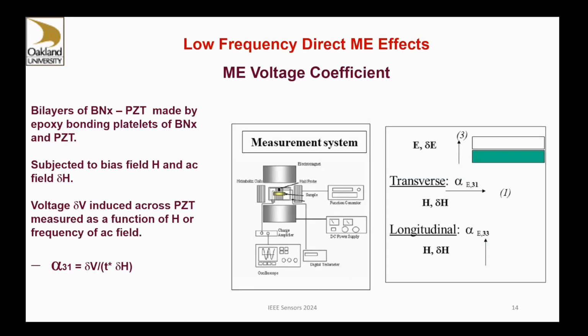So then what we did was to make a bilayer of these ferromagnetic platelets with PZT, and they were bonded by several different techniques, including epoxy bonding and eutectic bonding, and they were subjected to a DC magnetic field and then superimposed on it an AC field. And the voltage response was measured for two different field orientations.